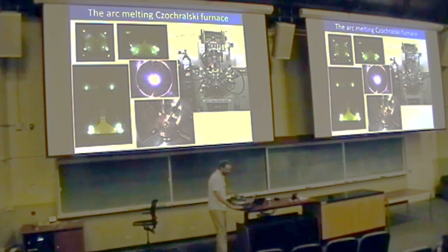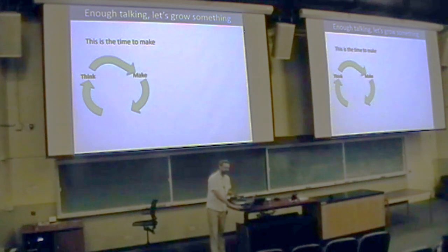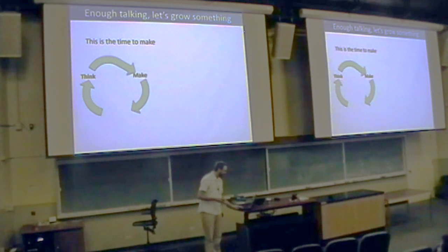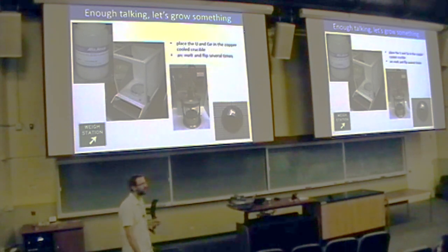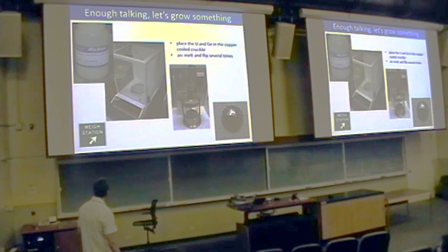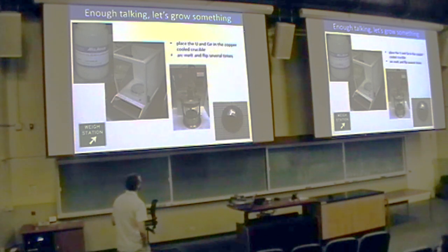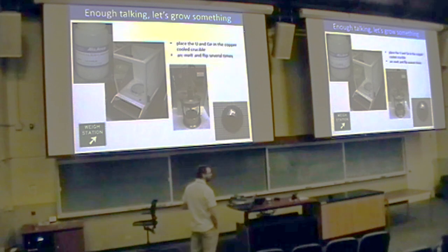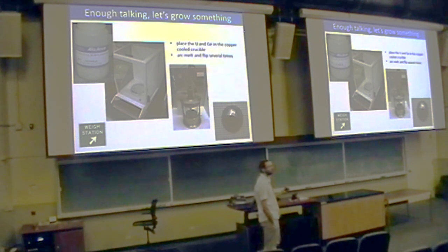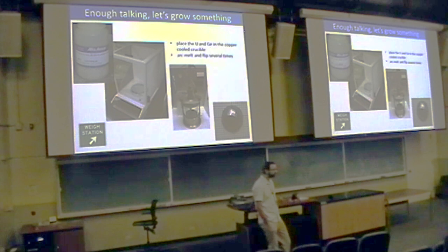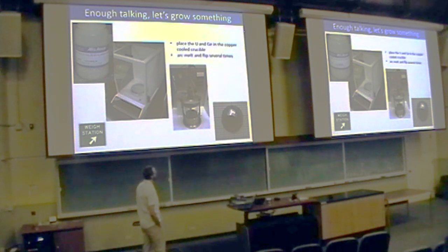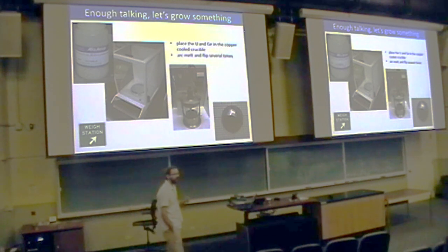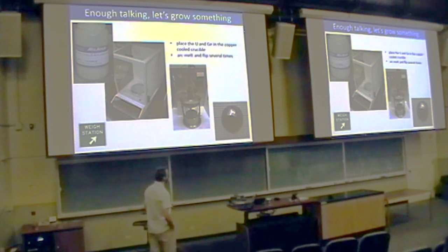Now again, that is nice, and this is the concept, but there are a few aspects to this. So again, you're going to start by weighing your material. You're going to go back to the scale and weigh uranium and germanium. This time you're going to use the exact stoichiometric ratio, so uranium 1, germanium 2. And then you can mix everything using a simple arc melting method, where you just melt without pulling first, to homogenize.